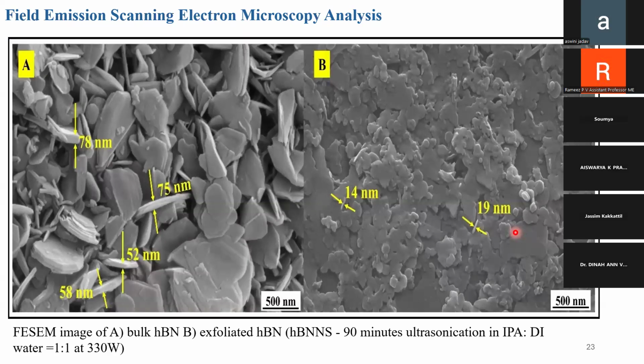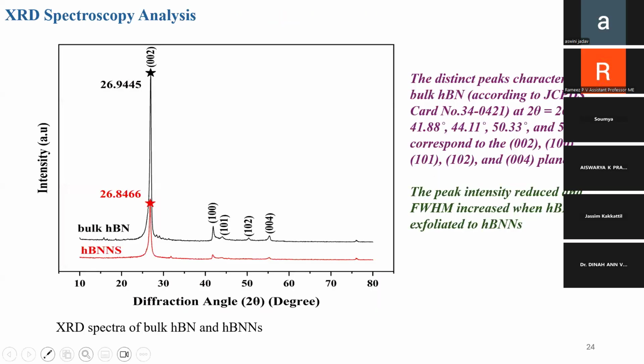Here you can see another image, field emission scanning electron microscopy, in which you can see the bulk thickness of the bulk HBN: 52 nanometers, 75 nanometers, 78 nanometers. These were the thicknesses before exfoliation. And it was brought down to 14 nanometers, 19 nanometers. That means effective exfoliation was carried out. Now this is the XRD spectroscopy. It will give you an idea of whether the crystal structure or atomic structure was preserved. This black one is the bulk HBN XRD spectrum.